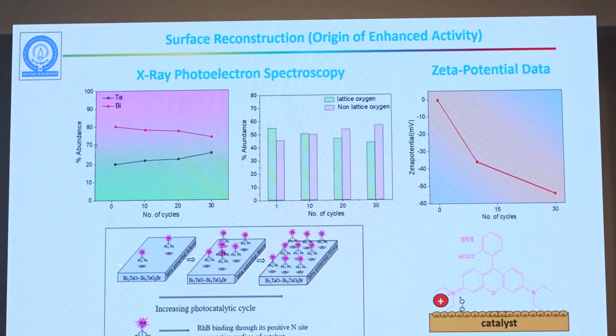Now, what happens in this process, when you do the reactions, the bismuth oxygen bond is weak, and bismuth and oxygen keep getting leached out to the solution. When that happens, we have defects on the surface, and these defects are negatively charged. And because this nitrogen is positively charged, it gets attracted and it sits in this inverted position, and that's why this deethylation happens. Now, as the time passes, the leaching is more and more. As a consequence, more and more molecules sit in this position and the self-activation happens.